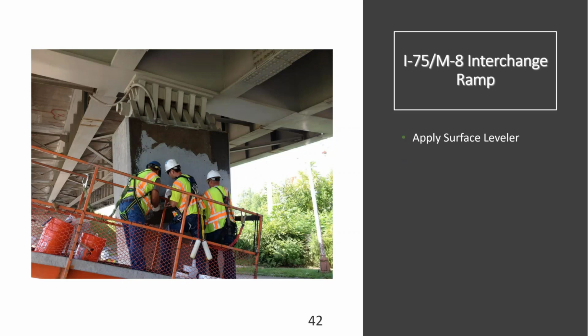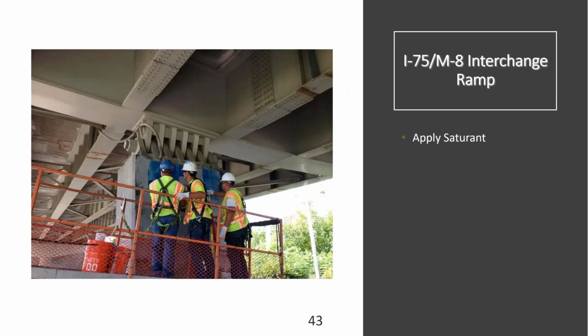what we are seeing here in the next step, which is the epoxy leveling putty. This basically fills in all the little tiny surface imperfections, voids, bug holes, to get a better adherence to the concrete. This is applied immediately after applying the primer. There's no cure time to wait in between. Immediately after applying the epoxy, we're applying a layer of the saturant.